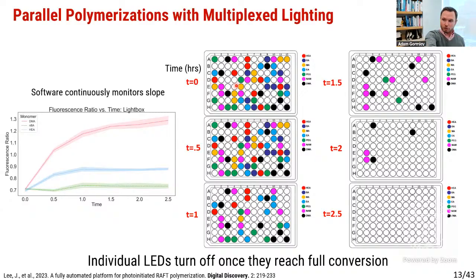It does this every 10 minutes: turns on the light, converts for 10 minutes, puts it in the UV-Vis, measures how much it converted, back and forth, back and forth. Because it's tracking conversion over time, as a polymerization reaction goes to completion, it turns the LED off, right? Because we no longer need to convert that reaction anymore. So what you're seeing here is that as time evolves, 0, 30 minutes, 1 hour, to 2.5 hours, the LEDs are slowly turning off because we no longer need to convert those reactions. By 2.5 hours, all of the polymerization reactions have reached full conversion. Everything is done. No reaction has received more light than it needed. This has been a really fun thing for us because it allows us to precisely control all of these different reaction mixtures in a very defined way.